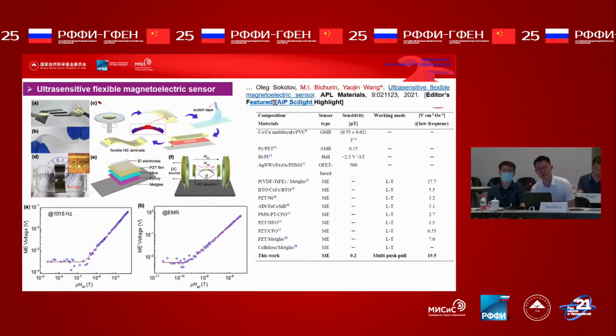The first one is the ultra-sensitive flexible magnetoelectric sensor. As we know, in previous studies the ME sensors were rigid ceramics. So here, we use a very interesting substrate, mica, which is like a 2D material. We deposit the PZT film on the mica and peel off the structure at the bottom. Then we make a flexible sensor.